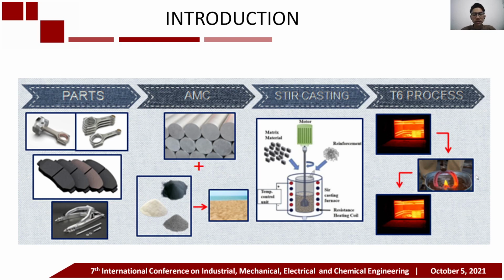Aluminum 6061 has a weakness in terms of strength. One of the methods used to increase its strength is heat treatment. Previous research explained that heat treatment with a cooling rate of various quenching agents affects the mechanical properties of the material. The faster the cooling rate, the higher the strength of the resulting material, but also distortion and cracks. For this reason, it is necessary to determine the optimum quenching media so that it can produce maximum mechanical properties on the Al6061-SiC composite.